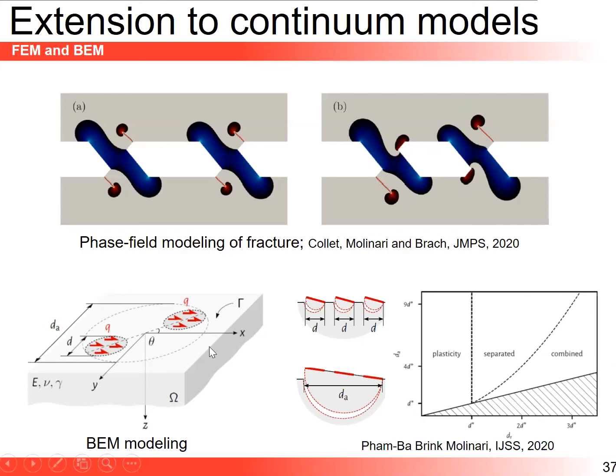We've also probed this, we cannot do this in a plasticity domain so easily, but with the BEM method, boundary element method, where we look here at a single body, and I'm turning to the study from a student in my lab, Son Famba. I know this figure is too small, but he looked at this in a 2D setting where he basically got an adhesive wear map depending on the space of those debris, where you transition from plasticity dominated to separate the debris versus large combined debris.